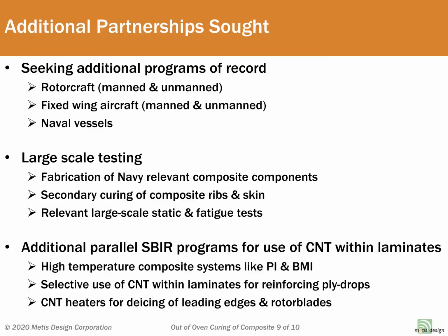Our current program is only addressing 350 Fahrenheit curing thermoset composite systems, but we have also had independent success looking at curing higher temperature thermoset laminates, processing thermoplastic laminates, and using the same approach for curing ribs to skin in secondary cures. We also are involved in complementary efforts using CNT technology to improve the static interlaminar performance of composite materials by as much as 25%, and improving the fatigue life by up to a factor of 10, as well as using the same CNT heating technology for integral de-icing that we've demonstrated for both fixed-wing aircraft as well as for rotor blades.